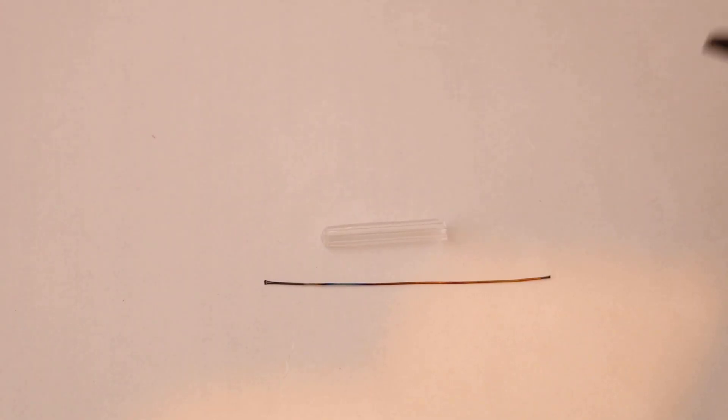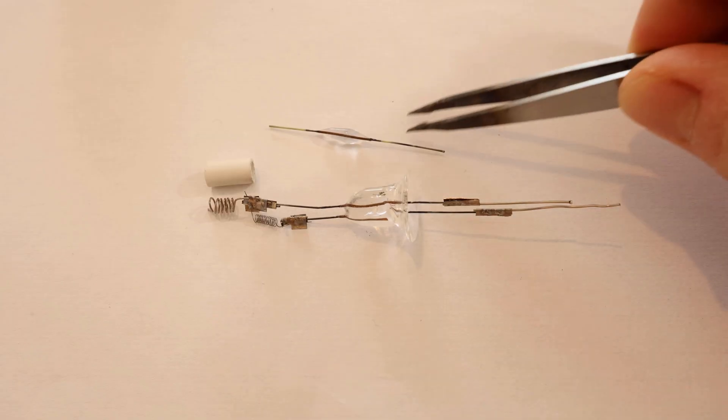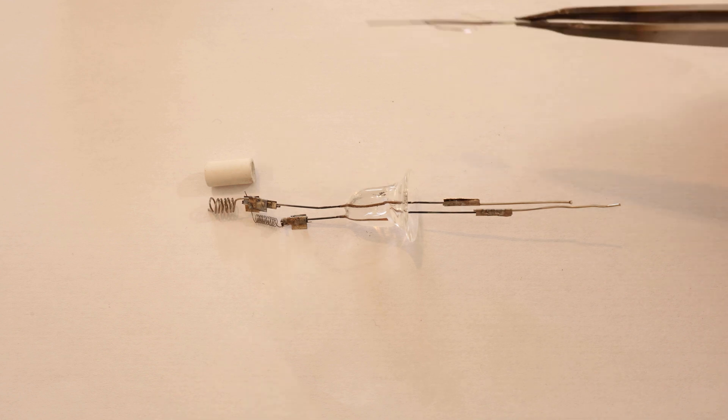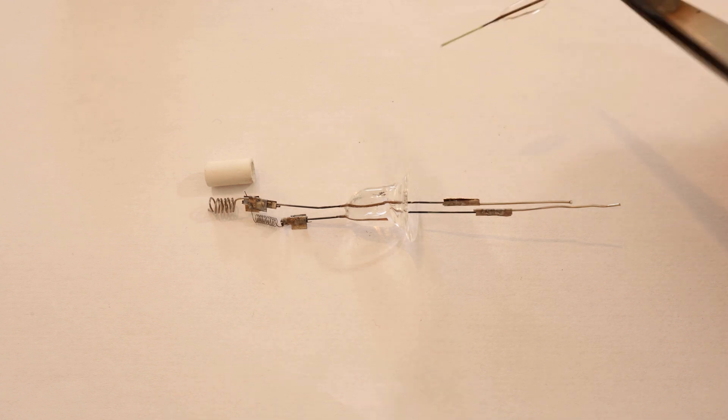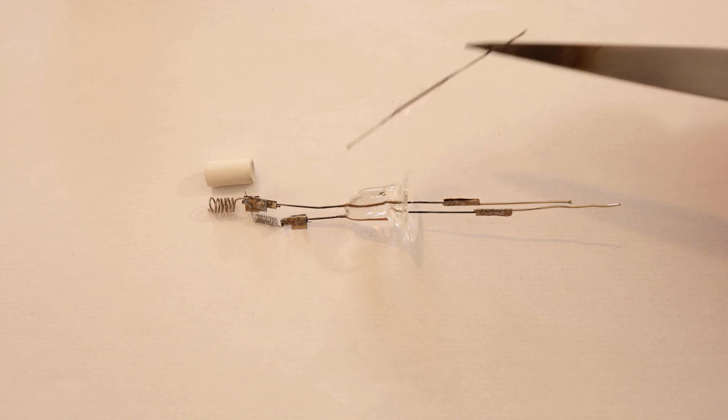And then I place a piece of glass around it and then heat it up in the torch very hot. And this should give you a seal with tungsten and glass that should be golden yellow or brown. And if it has this color it should be vacuum tight.